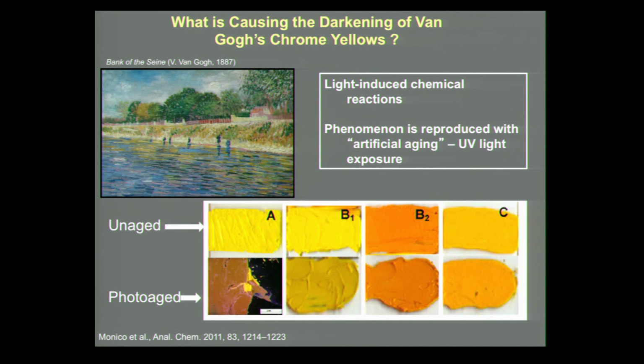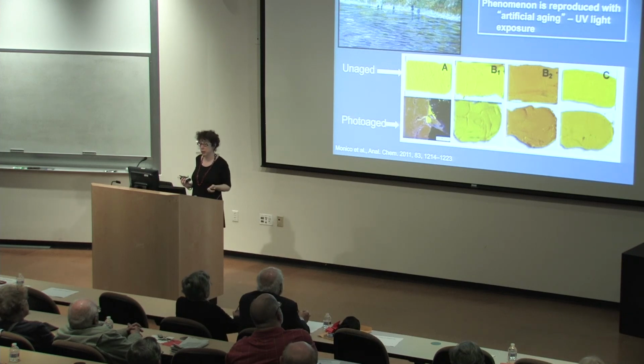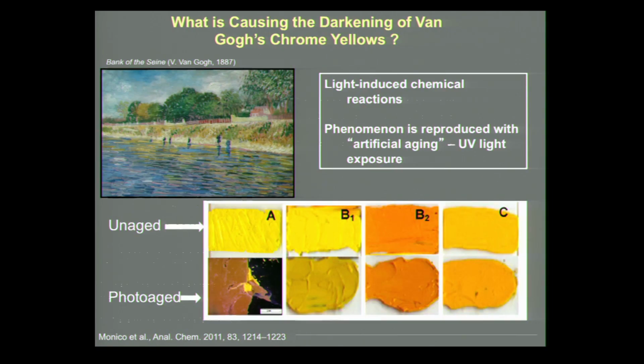And so here are samples that my colleagues made of unaged chrome yellow, and then after it's photo-aged, you can see that it's starting to turn brown on the surface, just like we see in the Van Gogh. And unfortunately, that dark surface on the painting is very, very thin. The scale bar here is 200 microns, and to give you a way to relate to that number, human hair, depending upon what part of the world you're from, varies between 50 and 100 microns. And the thickness of this darkened layer of the yellow paint is only about 3 microns or so. And so we have very little material to deal with in terms of the material we need to analyze.